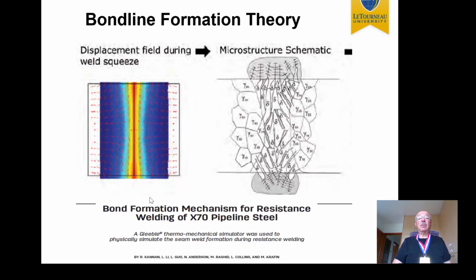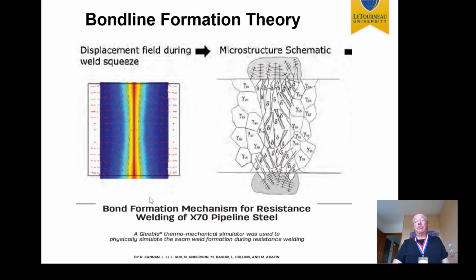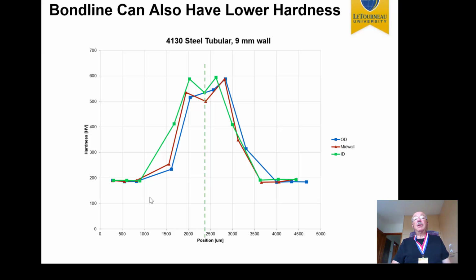and delta ferrite will be retained at the bond line. So this is not only my conclusion, but it is Dr. Lee's conclusion as well from the University of Alberta. He came to this conclusion totally independent of me. We also notice many times that in high alloy grades like 4130 tubular, where we have an increase in hardness from the base metal almost 3 times in the ERW weld, the center line, which is probably retained delta ferrite, has lower hardness right there. So that's not a decarburized layer, that's simply delta ferrite, period.